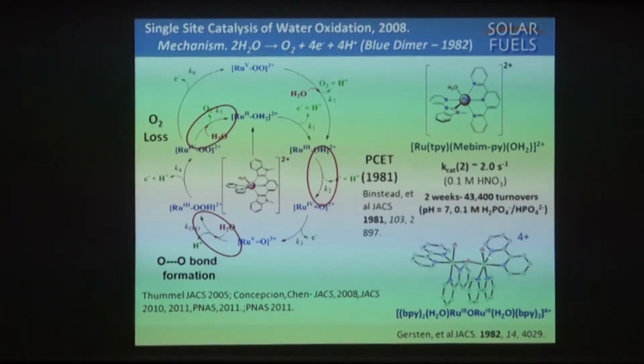Let me focus, instead of on this more complex system, on an example of a single site catalyst. Notice bipyridine ligands again. Here's a pyridine carbene. You'll see me use this complex 2 or 3 times more as I go on, so let me use it as an example. There's the water in the coordination sphere. The rate of water oxidation, the rate of turnover with this system, is relatively fast. I'll show you some data later. It is very robust. In an electrochemical experiment, for example, you can turn it over hundreds or certainly tens of thousands of times.